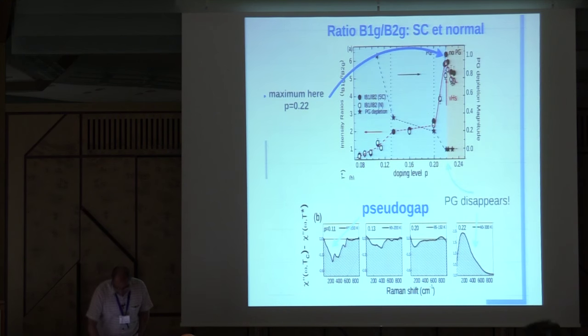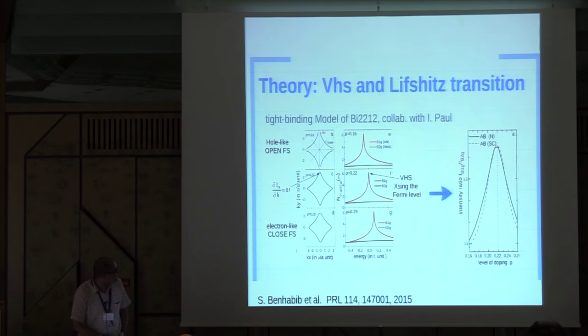So with my friend Idran and Paul, this is the detail of it, but we'll just skip it. We had an interpretation of this in terms of Lifshitz transition, namely in the Bi-based compound, which has two layers, so a bonding and anti-bonding band. One band at 22% goes through a Van Hove singularity, so a density of states which has a maximum, crossing the Fermi level. This can increase the Raman response, and right at this point. So we explain this in these terms.